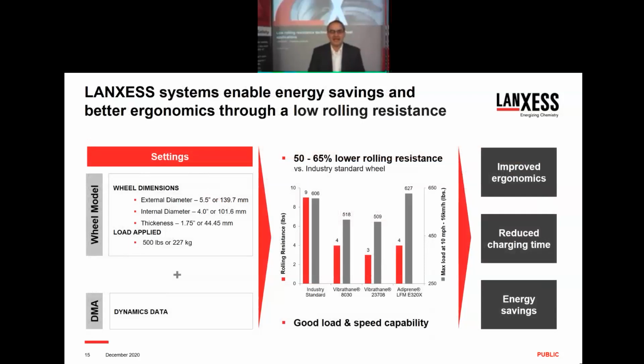So going back to this slide here, we were talking about the load capability of the different materials. Again, the industry standard on the left-hand side of this bar is a good urethane wheel. This in this particular case is an ether, but it's not focused on low rolling resistance. So it has a 9-pound per wheel rolling resistance. Whereas if you move to the 8030, which is the polycaprolactone, which is focused on low rolling resistance, it drops that about in half. If we look at purely the ether, the next one over, gets a little bit better rolling resistance, similar load capability to the polycaprolactone.